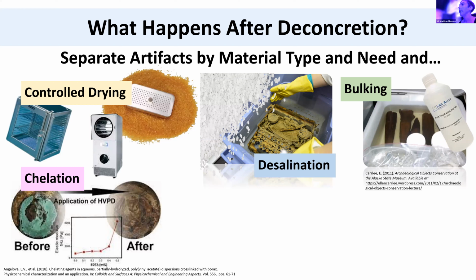So that can be very damaging, especially to organic materials or things that are kind of fragile, like ceramics, for example. If you have iron staining underneath a glaze layer of a ceramic, you can have basically corrosion happening inside your glaze layer, which often means that you physically lose your glaze layer. Either it's dissolved by acidic attack, or it's physically broken off by the growth of corrosion inside. So we try to remove iron that has migrated onto things that are not iron through a process called chelation, which basically is a chemical treatment where we introduce a special type of molecule that is designed to bind to metal cations and remove them from the artifacts.